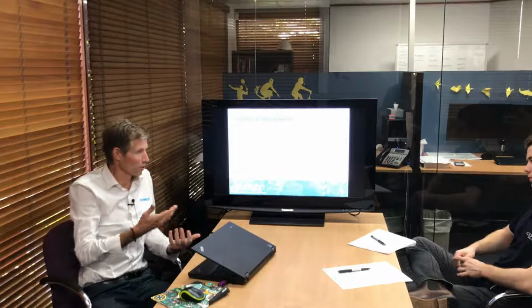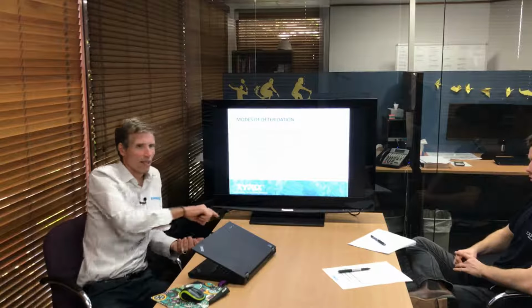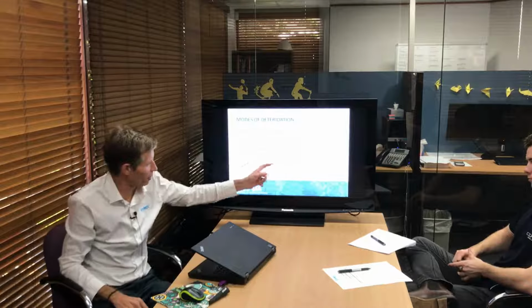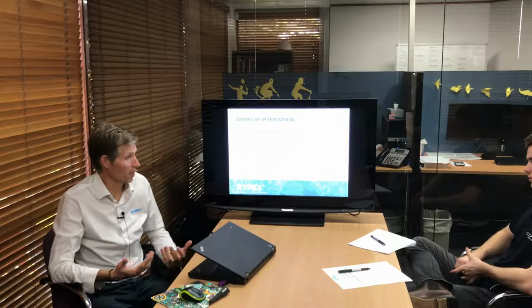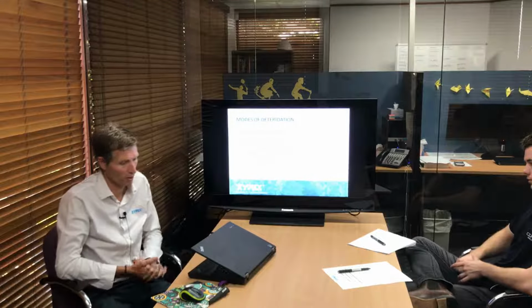That means the ettringite crystals don't form during the hydration process of the concrete, during normal curing. And as it said there, it's a delayed reaction. So that can show up further down the line with the introduction of water and then cause cracking and things. It creates a problem very similar to AAR. But as I say, it's more prevalent in mass pour high strength concretes and also in precast, when you're trying to get really high strength gains very quickly to move the elements along the production line.